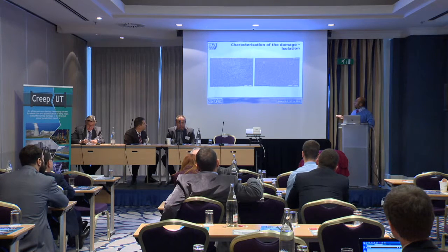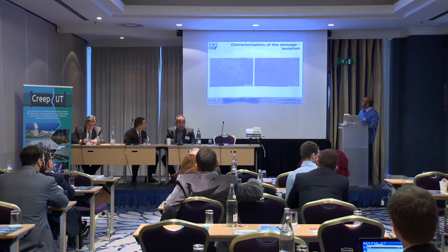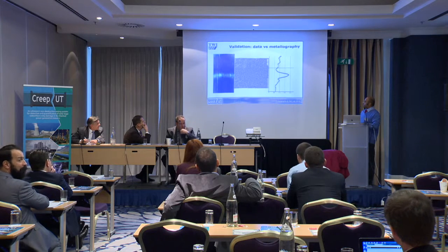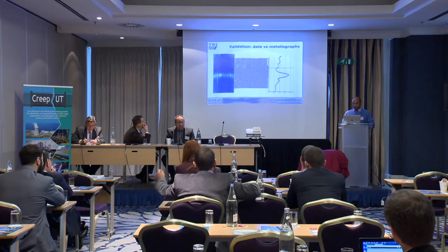And when we look even closer, you can see the damage at various different levels. So 50 microns here, and then 300 microns there. So it was possible to get a range of damage in specimens. And when you look at the data, this is data collected from the CreepUT by KTU, and you put the data adjacent to the damage, and then using a processed parameter, it was clear that the signal to noise here is easy to interpret that there is a microstructural change at that position in the metal. And so that's essentially the premise for the Creep test system.